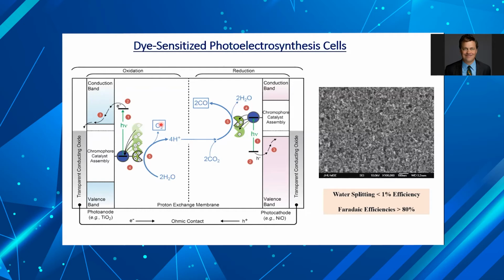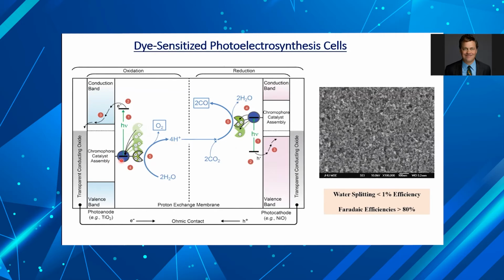And that's much more challenging than oxidizing something like iodide. In general, the sensitizer or dye itself, although it can be thermodynamically capable of driving the reaction, kinetically can't do it fast enough because the electrons that are injected will recombine too quickly. So we use what we call chromophore catalysts, where there's a light absorbing dye shown as this blue sphere, and then these Pac-Man type creatures are the molecular catalysts. And I'll show you a specific example of that later in my talk. But we need to have 4 interfacial charge transfer events before we can make the oxygen-oxygen double bond.